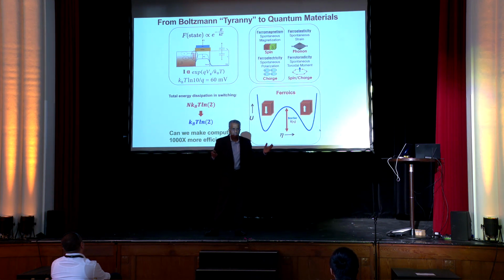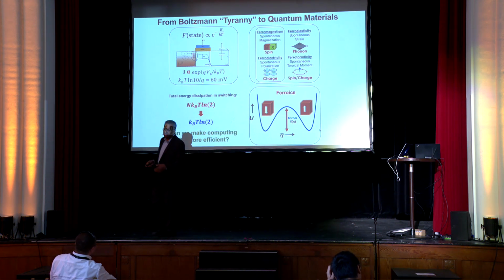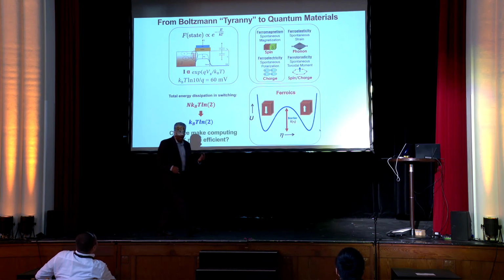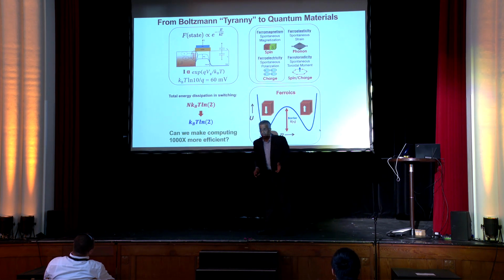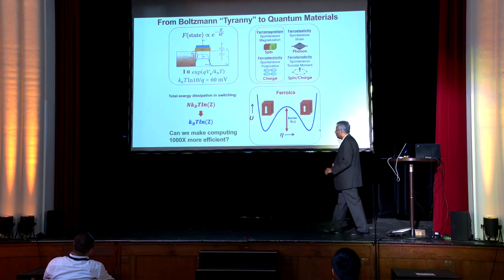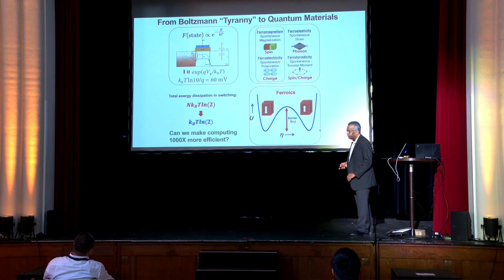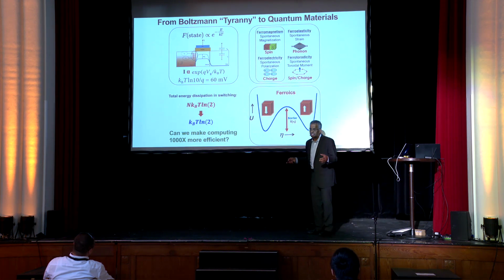Today it's about maybe 20 picojoules per operation. Can we go down to femtojoules? In our case, we want to go to attojoules. So appropriately for Atocube, we want to do it at 1 attojoule per operation. Now, it's not impossible. It's still not the Landauer limit. It's still far from the Landauer limit. It's of the order of 100 kT. So we could use ferromagnets, ferroelectrics, order parameters in some sense to do this.